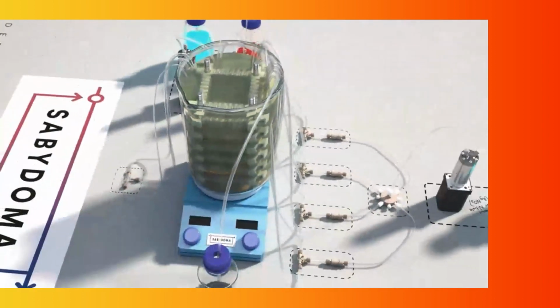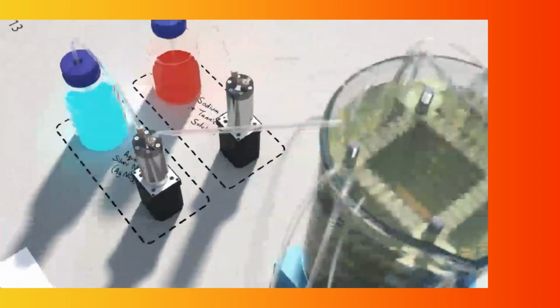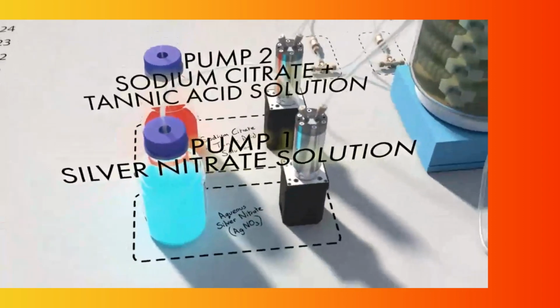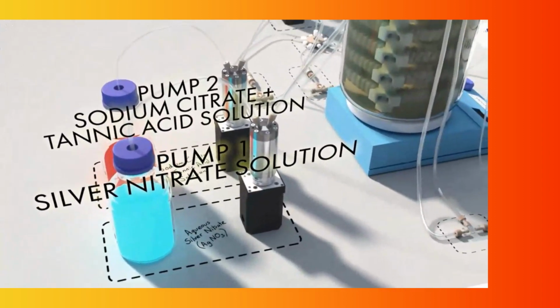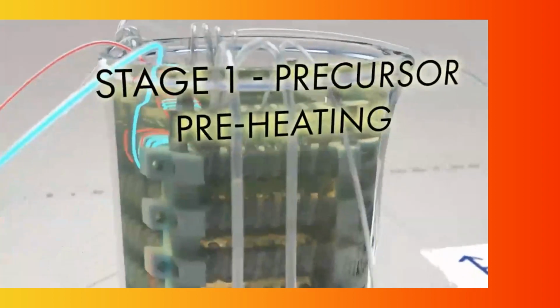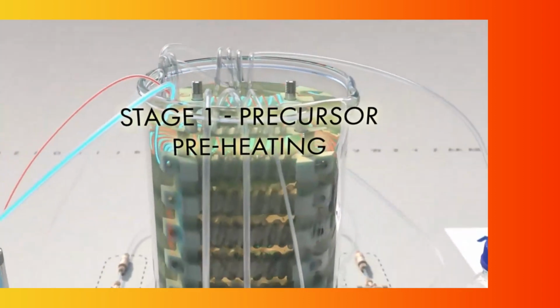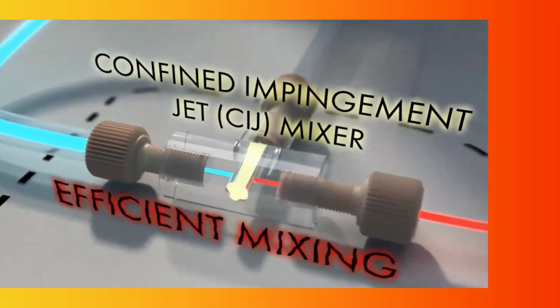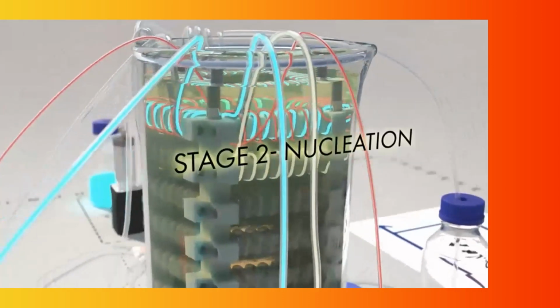And you can see that the different flows are introduced. There's the silver nitrate and then the reductant. They're preheated in the oil bath, and then they come out of the oil bath at a fixed temperature. They're mixed at this T piece. In this case, it's a CIJ mixer. Then the nanoparticles are formed.